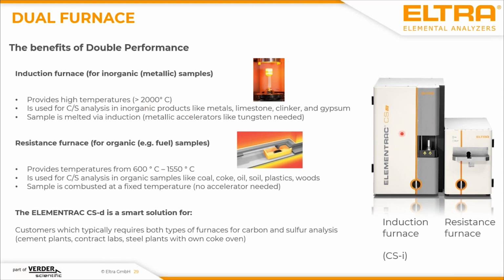Additionally, we have an induction furnace. This is this part here. You know, induction oven from your kitchen might be, and the induction furnace has some advantages. The main advantage is the higher temperature. You see more than 2000 degrees centigrade. And this cracks really everything in your cement sample. Some sulfur bondings inside your cement sample are very, very strong. And if you have the suspicion that your sulfur content you measure is too low, then try it in the induction furnace. And if you get a higher content there, then you see that the bonding is too strong for the resistance furnace.